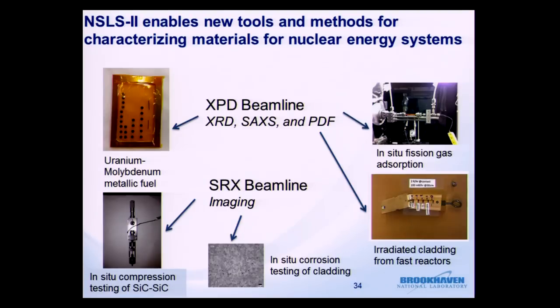And then as a final example, I'll mention that we looked at the in situ adsorption of fission gas. So during the fissioning process, fission gas, largely xenon and krypton, is generated, and this can build up and pressurize the inside of the cladding. So adsorbing that could potentially reduce the pressure and allow for higher burnups in the fuel. We used a metal organic framework to try to absorb xenon. We were able to perform an in situ experiment where we put the metal organic framework here and flowed the xenon past at the light source. And by combining the diffraction results with computational studies, we were able to determine the sites in the metal organic framework where the xenon was being absorbed.